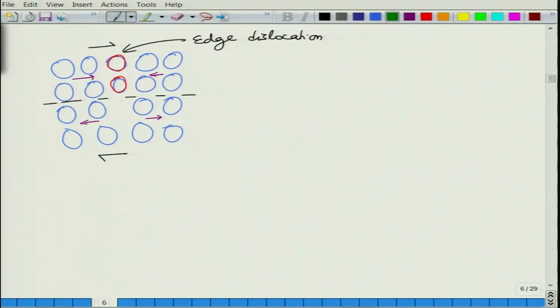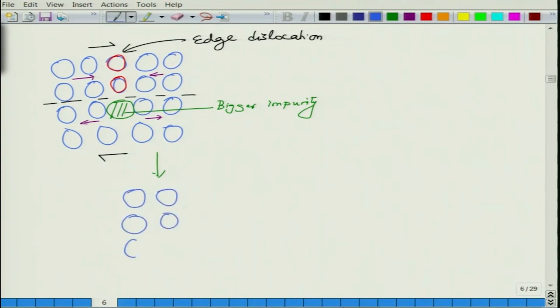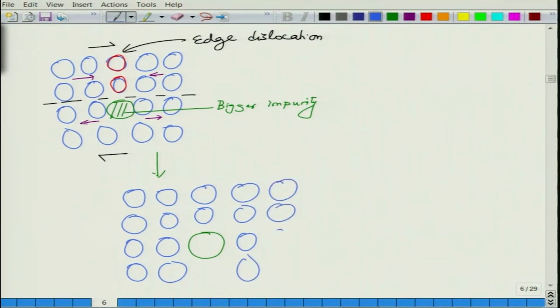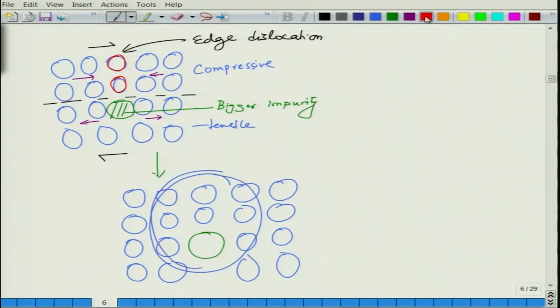So, what I do is that now if I put an impurity here which is bigger, so this is a bigger impurity, and the bigger impurity will dilate the lattice. So, if I do that, then you have a situation like this. And this is the bigger atom. So, you can see now the top portion was under compressive stresses, the bottom was under tensile stresses. So, this is compressive and this is tensile. Now, you have put this bigger atom, you have expanded the bottom part. So, the stresses in the top and bottom counterbalance each other. So, basically you can see that the dislocation has now become attached to the impurity, and it becomes more stable.